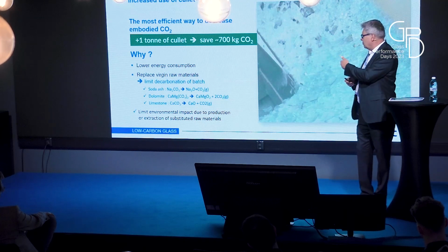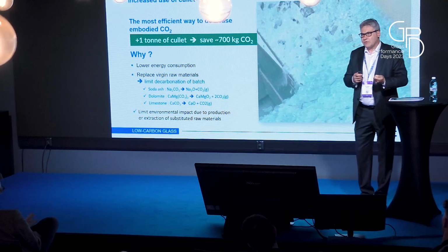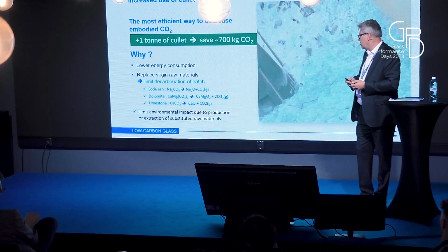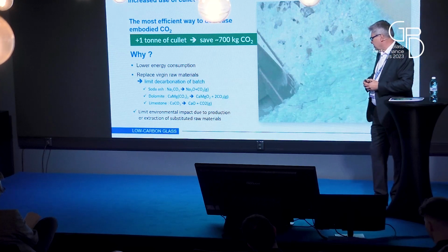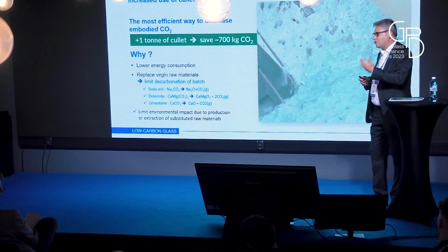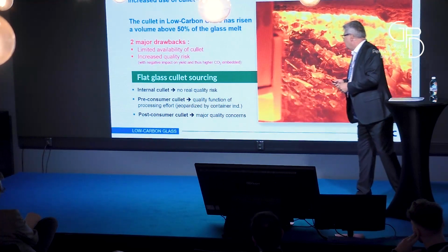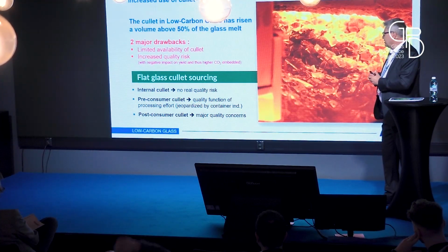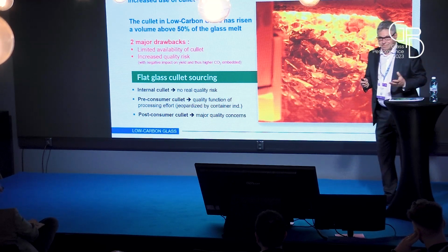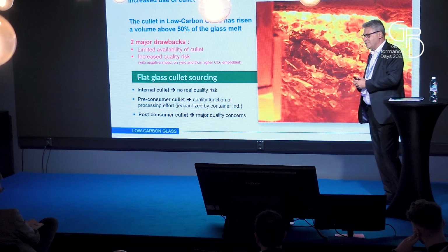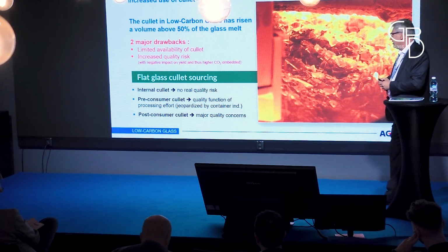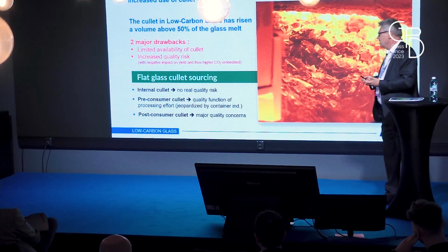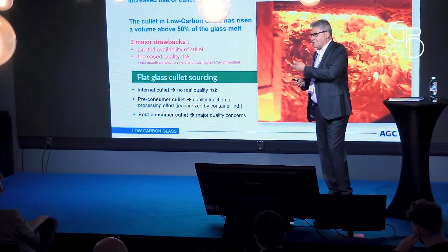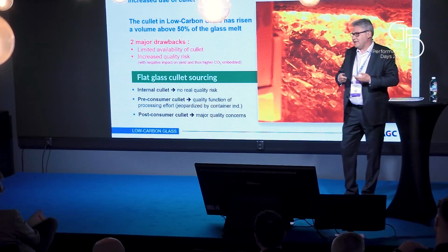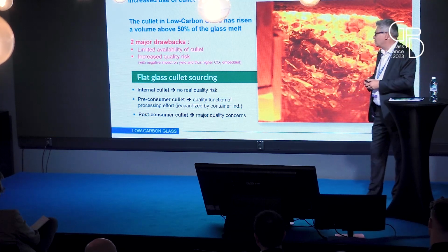Normally, when you add soda ash, dolomite, limestone, all this raw material, when it melts, it emits some CO2, and you have the chemistry equation there. And of course, it limits the impact due to the production of this material that we do not put inside the furnace. But there are two major drawbacks. The limited availability of the cullet, which we discussed in different presentations yesterday. And it increases the quality risk also. If we have too many impurities in the cullet, as I explained, it has an impact on the yield, and finally, it has a bad impact on the CO2 balance.